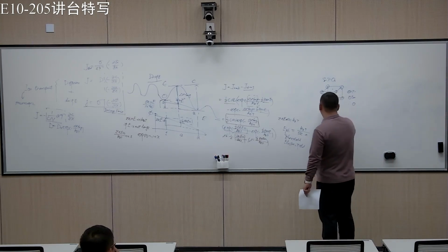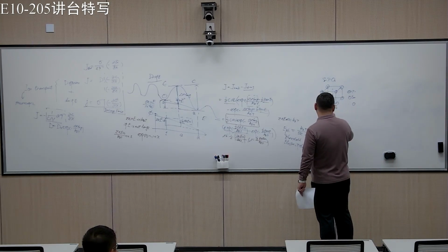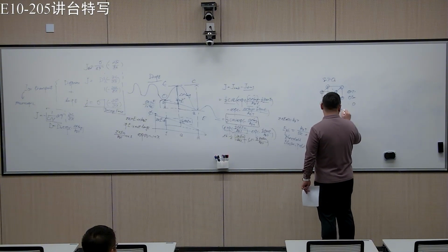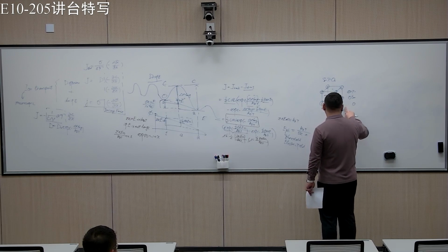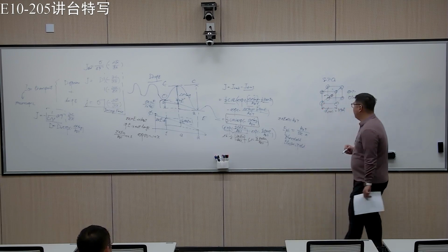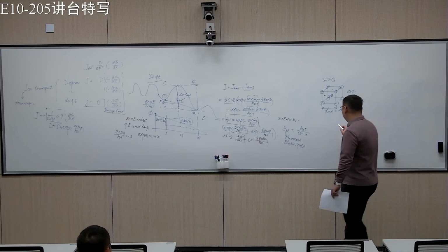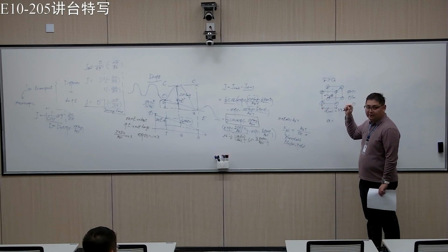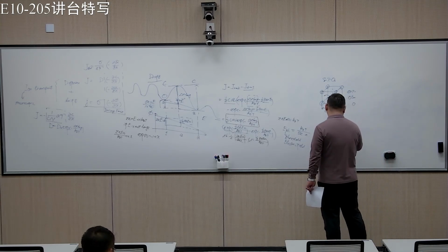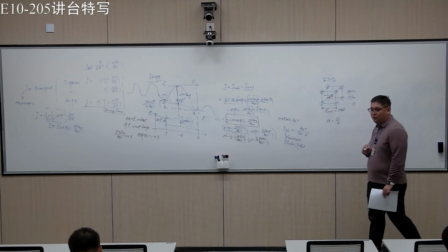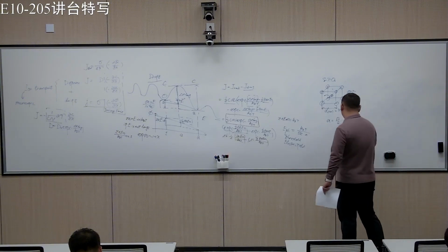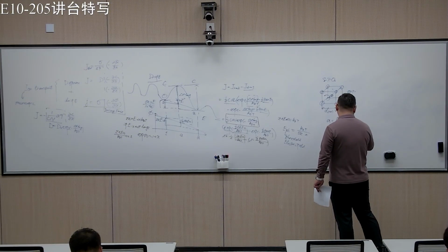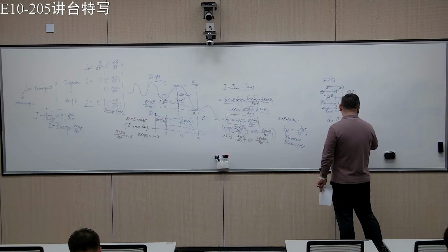So we know that the atomic distance, the lattice parameter, is 3.9 angstrom. Okay, so then A means from this side to that side. Okay, so basically that's square root of 2 divided by 2 times the lattice constant, which is roughly 2.76 angstrom. Okay.